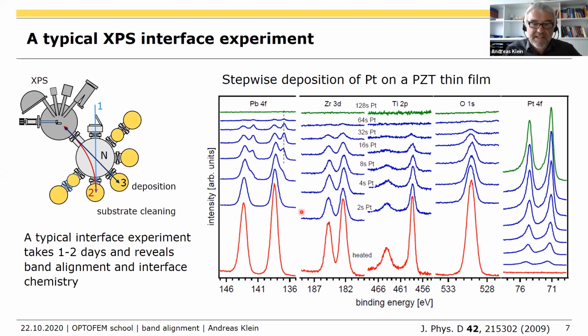The reason why you get metallic lead here is that these lead atoms which you deposit are coming from the gas phase, and they are isolated atoms without any chemical bonds. If they condense at the surface, they will form chemical bonds with the surface. And these chemical bonds have a binding energy of, let's say, a few electron volts. The release of the condensation energy of these metal atoms, that's what we believe, and this has also been proposed quite some time ago in literature, is causing some reduction, some formation of oxygen vacancies.